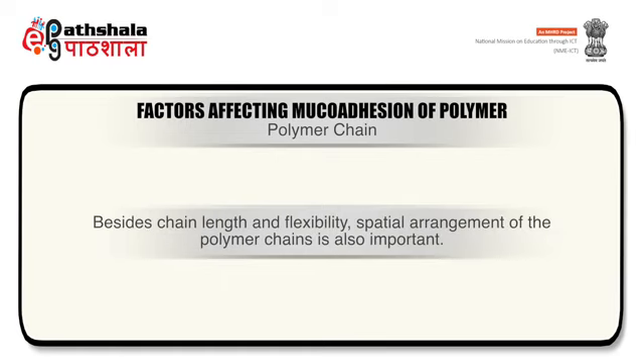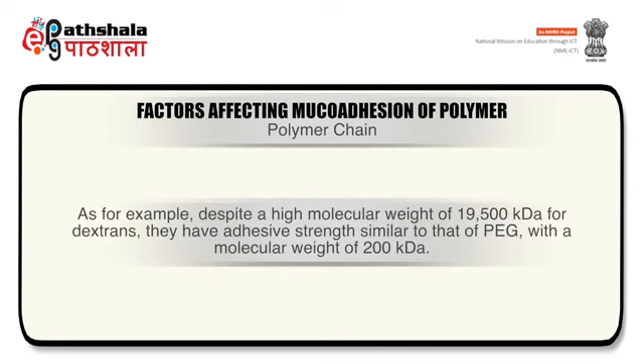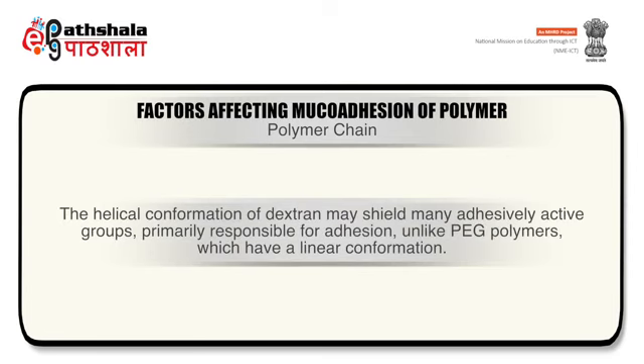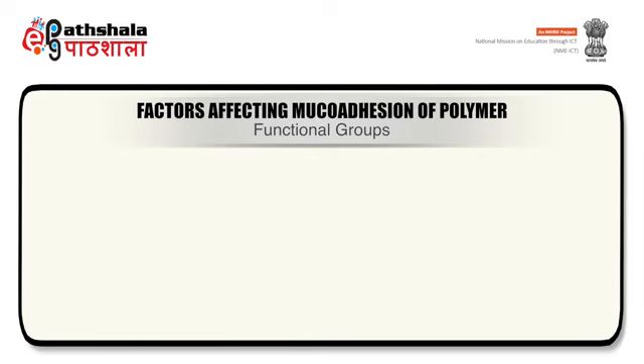Besides chain length and flexibility, the spatial arrangement of the polymer chain is also an important parameter. For example, despite a high molecular weight of 19,500 kilodaltons for dextran, they have adhesive properties similar to that of PEG with a molecular weight of 200 kilodaltons. The helical conformation of dextran may shield many adhesive active groups primarily responsible for adhesion, unlike PEG polymers which have a linear conformation. The next parameter to discuss is functional groups.